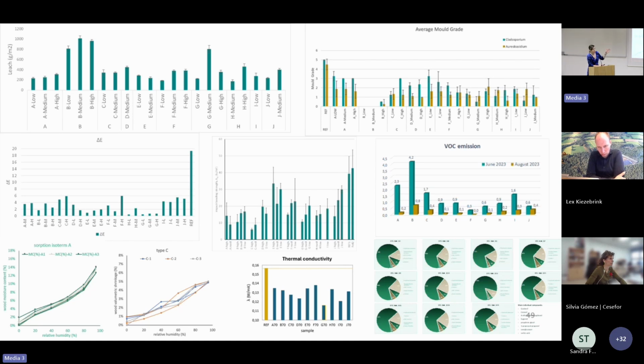Even the VOC emission, for example, you can smell nice barbecue smell from the wood. The VOC tests were able to prove that the VOC is not problematic. The thermal conductivity was done, and the sorption, desorption, shrinkage, swelling, all of these properties.